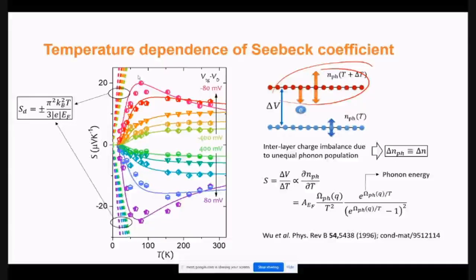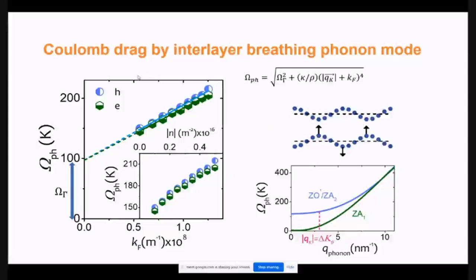Okay, so you're absolutely right, in both the ideas. So anyway, we have found that if you don't do anything, then it's the hybridization of the two phonons, two layers in terms of crystal lattice vibration, essentially dominates the electron transfer from one layer to the other. Alternatively, we can say what we really are seeing is a Coulomb drag at the atomic scale.